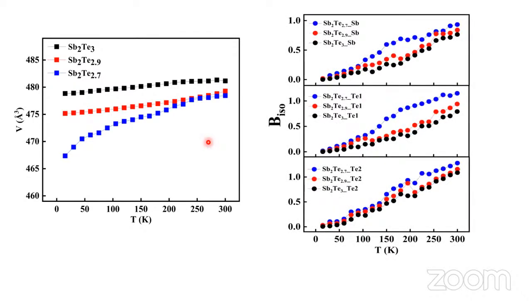where BISO, that means the isotropic thermal factor, is increasing with temperature for all the atomic positions. And you can see that for all the atomic positions, BISO values increase with tellurium vacancy. That proves the defects are increasing with tellurium vacancy, and the defects are mainly SbTe anti-site defects.